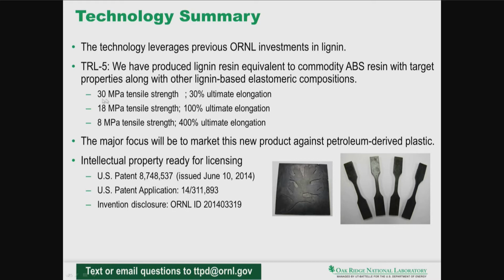So far we have demonstrated 30 megapascal tensile strength with 30% ultimate elongation. ABS may have 35 megapascal and 5% ultimate elongation. Also, some products can be categorized as halfway through that, 18 megapascal tensile strength but 100% ultimate elongation. Some materials are a little soft or rubbery, at 8 megapascal tensile strength and 400% ultimate elongation. So depending on the selection of lignin or additive, we can categorize different products. I would say the top one would be engineering plastics equivalent, and the bottom one would be almost like rubbery materials.